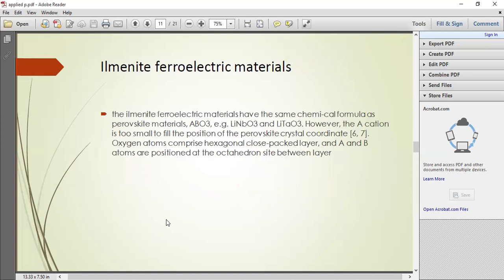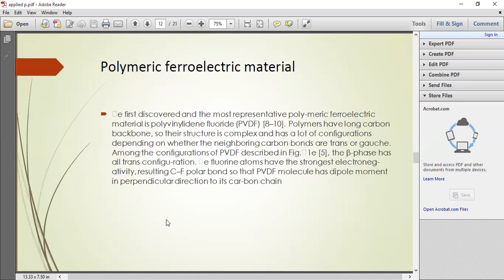Ilmenite ferroelectric materials have the same chemical formula as perovskite ferroelectric materials. However, the cation is too small to fill the position in the perovskite crystal. Coordinated oxygen atoms comprise hexagonal close packed layers. A and B atoms are positioned at the octahedral sites between the layers. Polymer ferroelectric materials were also discovered, and the most representative polymer ferroelectric material is polyvinylidene fluoride (PVDF).